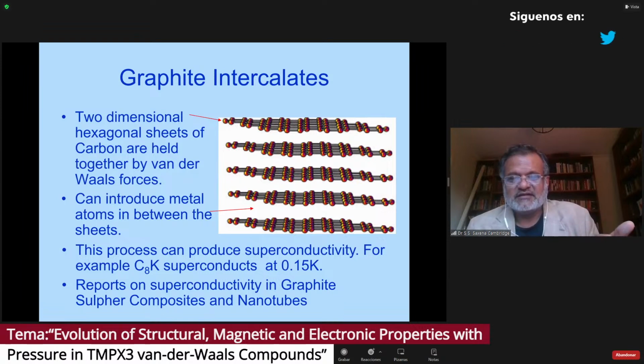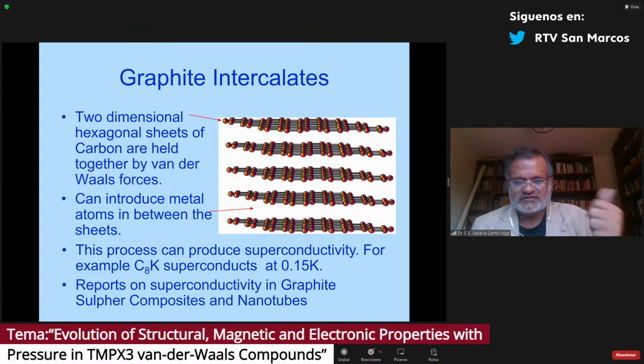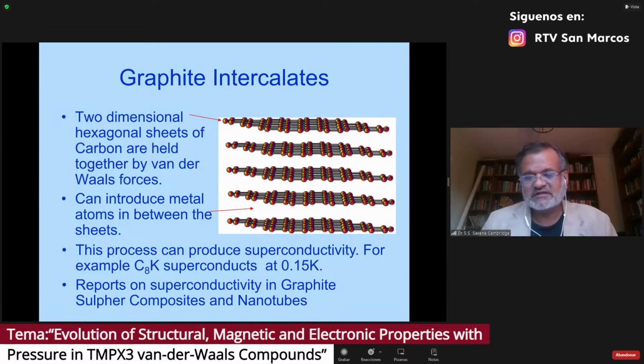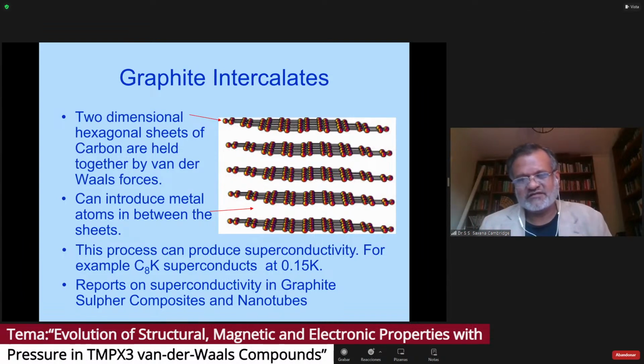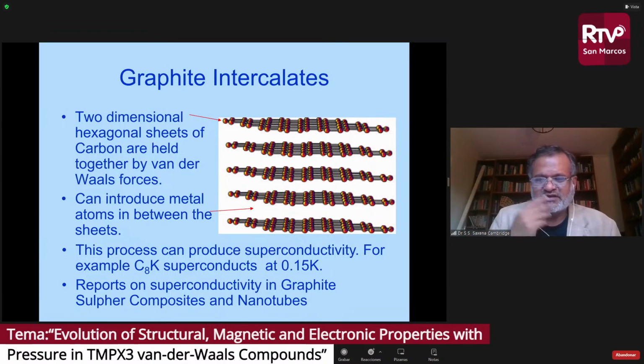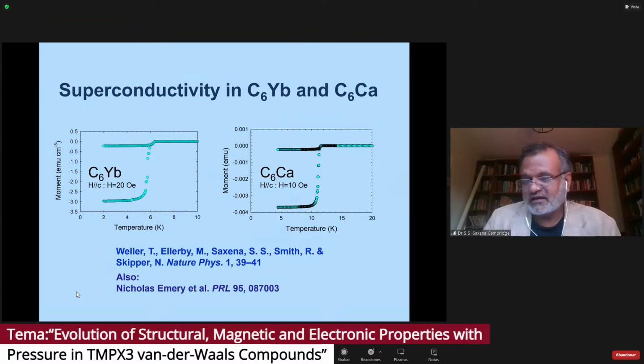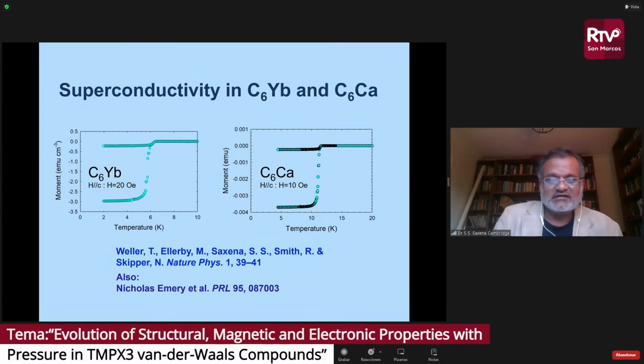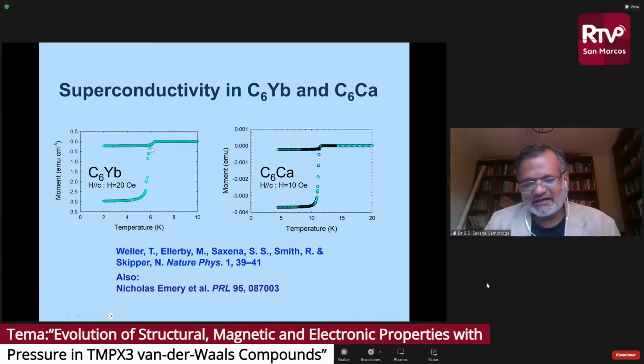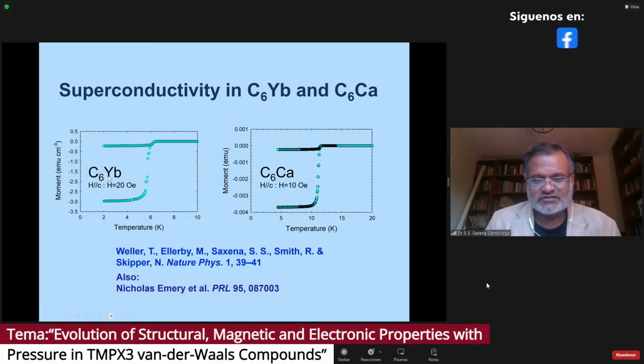will create two opportunities for novel magnetism and possible superconductivity. The first scenario is that you have next nearest neighbor frustration, and that will create fluctuations in the system. The second one is that if you apply pressure, we can tune the ytterbium from 2+ to 3+, and that can lead to, again, more magnetic fluctuations in the d layers, and possibly create new superconductivity or other states. So this is what we started with, and in fact, we were quite lucky to find superconductivity in C6 ytterbium at a very high temperature for that era, and even now, it was one of the highest TC graphite-based superconductors.